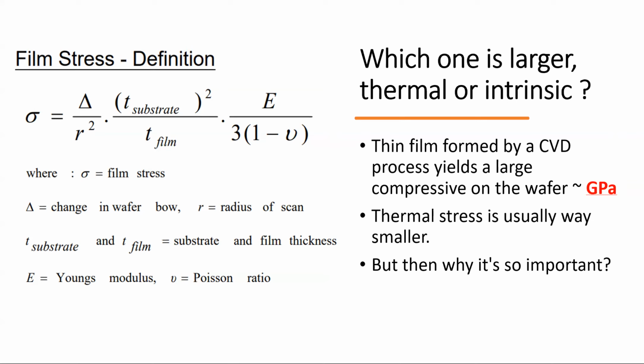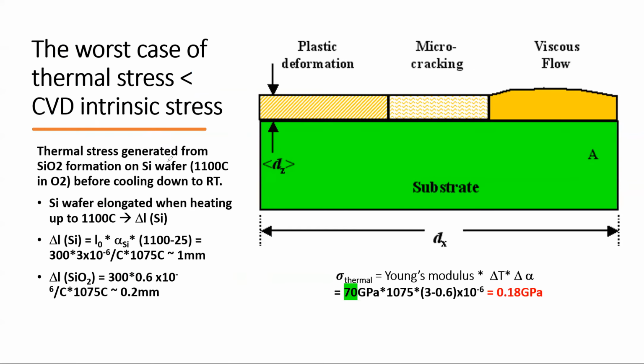But if you look at an extreme example of a thermal stress: the thermal stress generated from SiO2 formation on a silicon wafer, which is pushed to about 1100 C in oxygen or moisture (H2O) before cooling down to room temperature. Then we would like to calculate the thermal stress from this thermal history. The silicon wafer elongates when heating up to 1100. Everything elongates at high temperature, just to a different degree. Silicon will expand sideways by 1 millimeter, but the SiO2 formed on top can only do 20% of that. The difference between these two creates the stress. That is a real thermal stress.